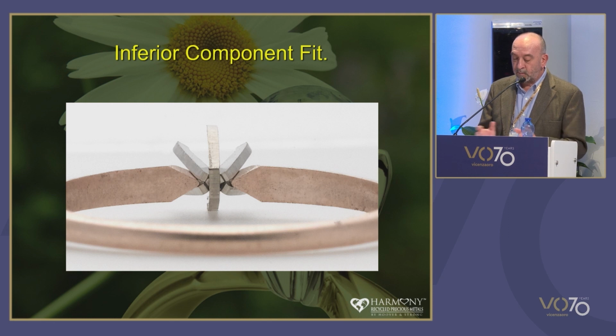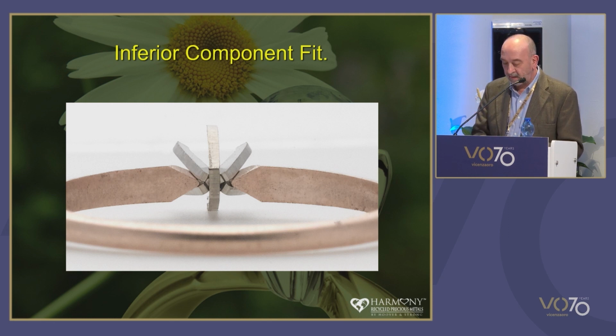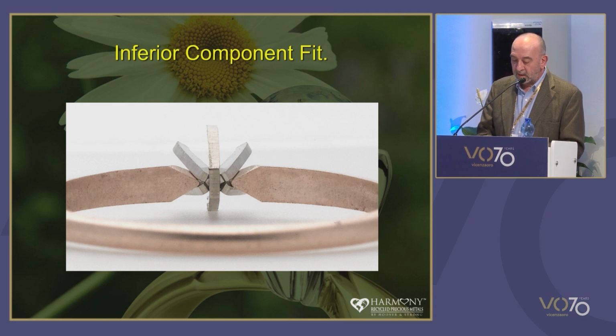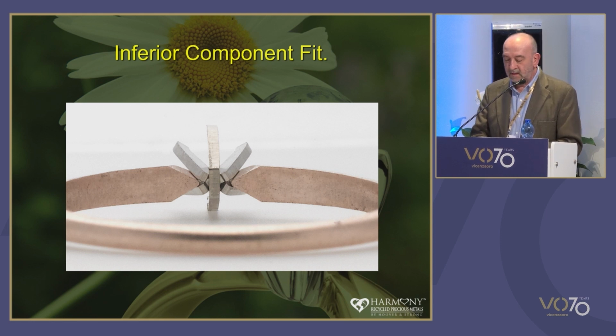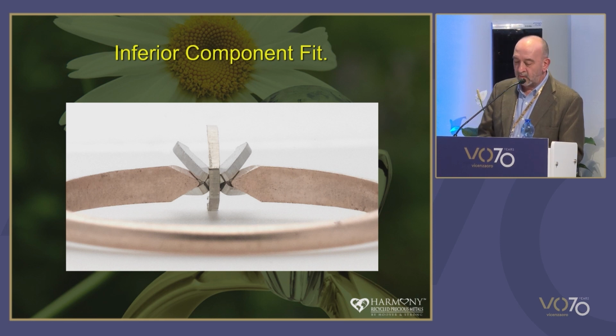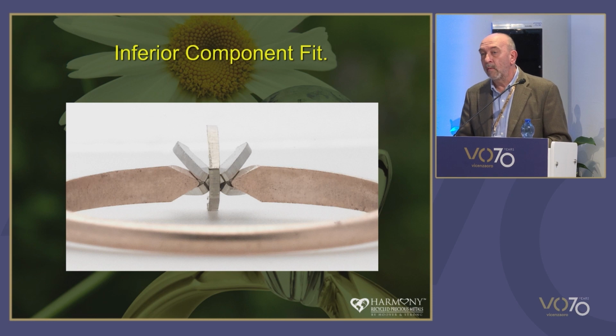It resulted in the presence of these big voids, and so the solder was acting as a filler, not just a joiner. After soldering through the belt furnace, the components were joined, but not to a satisfactory standard that could be finished without repair work. And the porosity identified was, as you see, voids generated by a function of poor component fit. So we removed the pre-finishing step and the joint quality improved and we were back to normal.